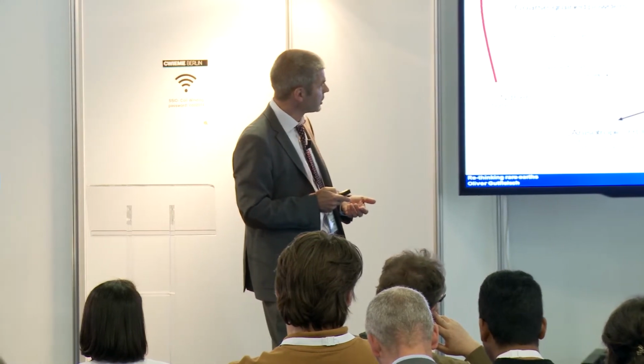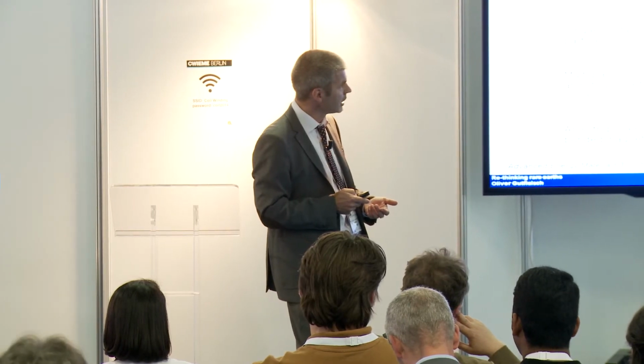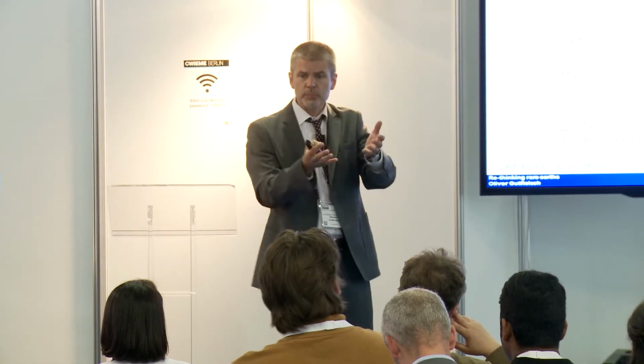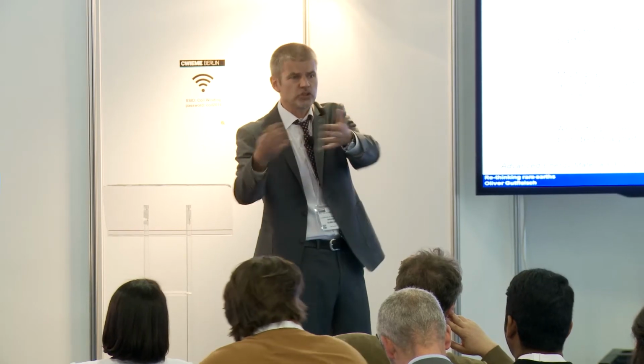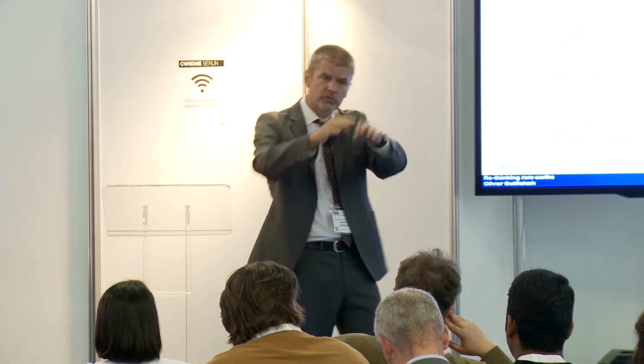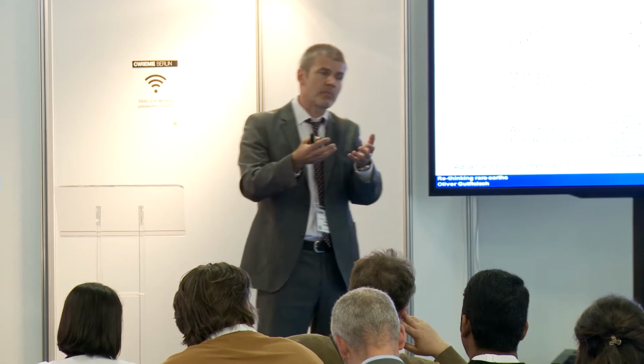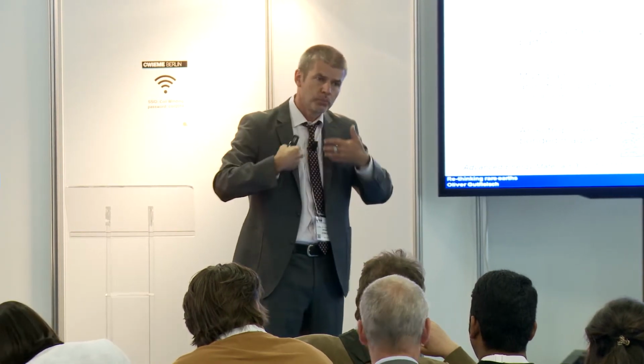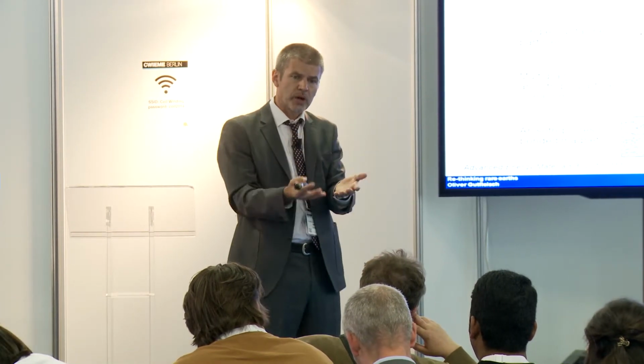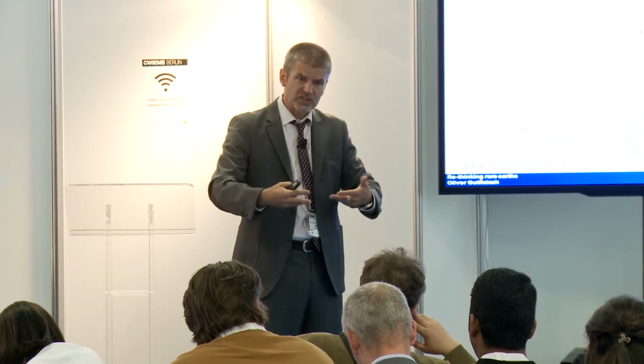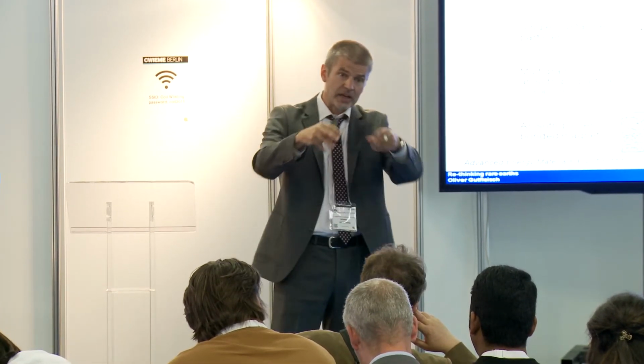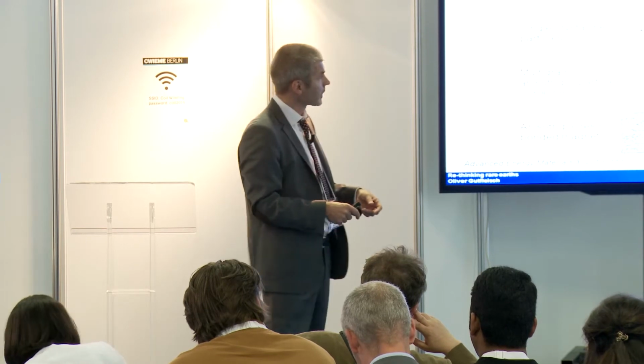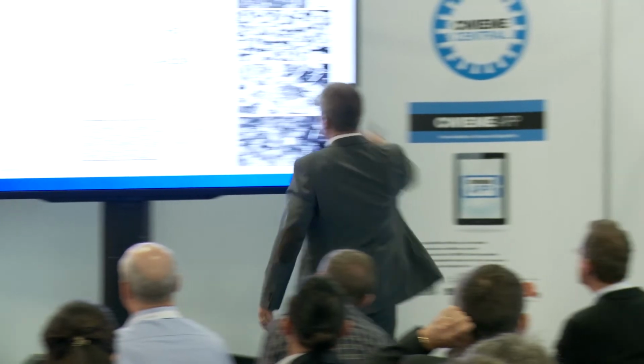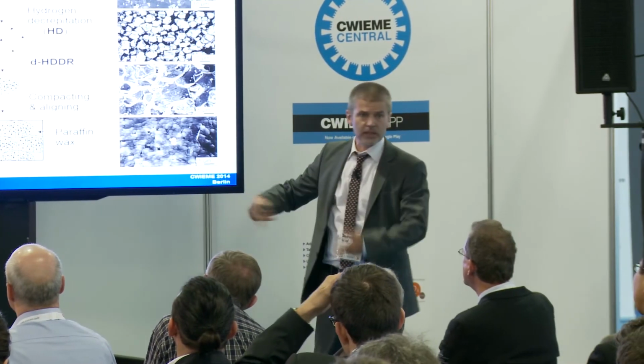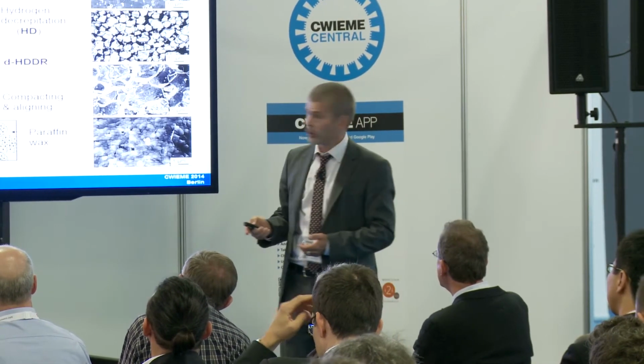I will be quick here, not go into the detail. What we basically do is use a scrap sintered magnet from a disused motor, take the magnet-containing component out, and put hydrogen over it. The magnet powder will basically fall out because it's so reactive. The rare earths, they love hydrogen, they jump on it. And then we have a very clean single crystal powder here, and this we can make into a reasonably good polymer bonded magnet.